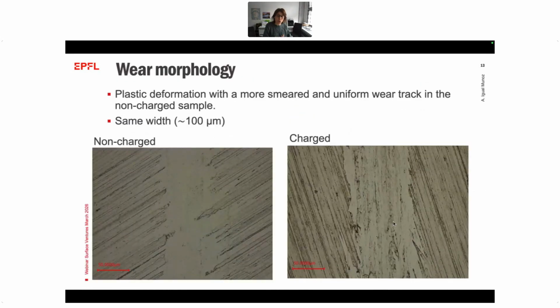Then we go to see what happens on the surface, and this is the optical image of the non-charged and charged samples. And we see in the non-charged this kind of nice plastic deformation with this smear and uniform wear track. The width of the wear track is more or less the same, and in the charged sample, it seems that we are blocking the plastic deformation, like we were generating more disrupted surfaces. So we see already differences.